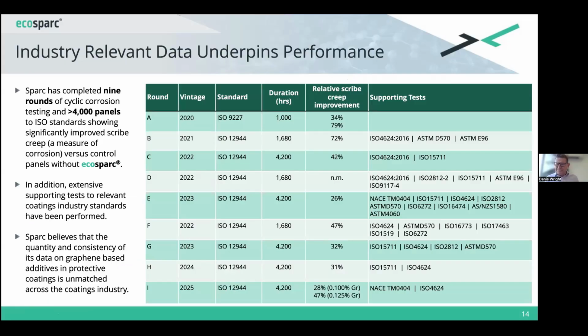This slide, the point of this slide is to demonstrate the amount of work that we've done. So rounds A to I there, round A 5 or 6 years ago, that's 9 rounds of 12944 type testing. For those who aren't actively within paint, that's a 6-month test, 4,200 hours, hundreds of panels. We do things as per standard, duplicate, triplicate as necessary, scribe creep measurements. And so we've gone through that process 9 times. The data that we generate out of each of them feeds into the next generation of work that we're doing or confirms with internal standards between rounds. I know there's a lot of mouthful there, but that's just how it works.